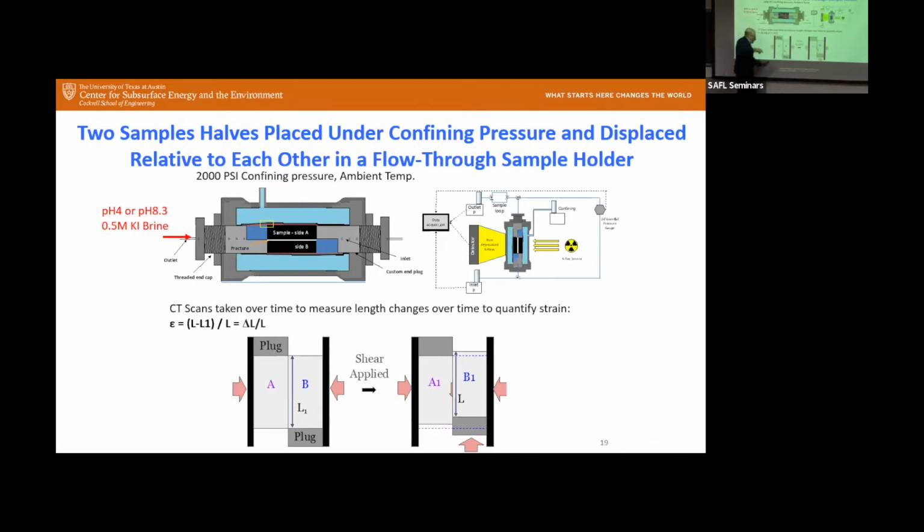And when you do that, when you initially move this plug up, you move this part up, but this part doesn't initially move. And then over time, so it's under strain, and over time then, as the strain is released, this side will slowly move until the whole thing is displaced, okay? So initially you move it, this end piece stays fixed even though you move this side, because those asperities are locked in, and over time those asperities give way, right? The strain is released, and then that moves up, and we measure that strain release, right?